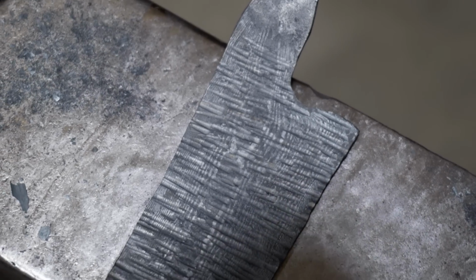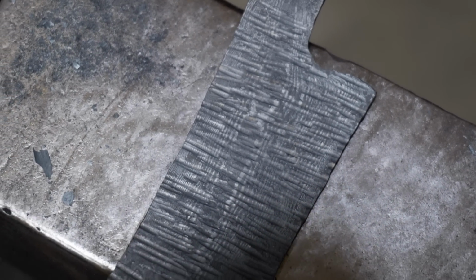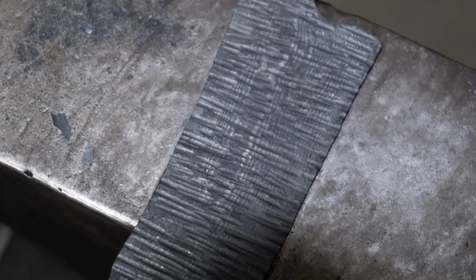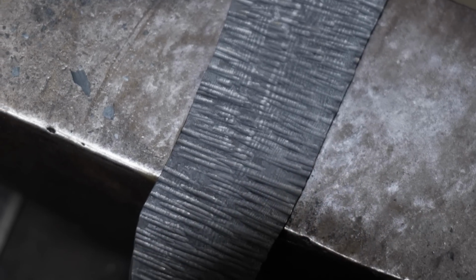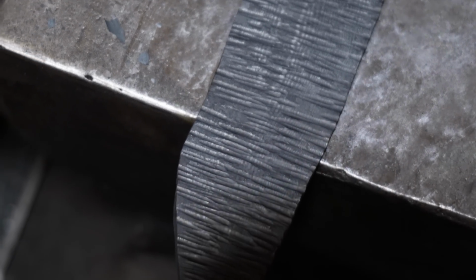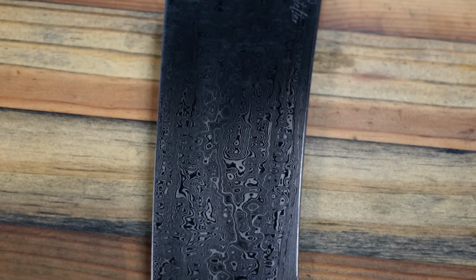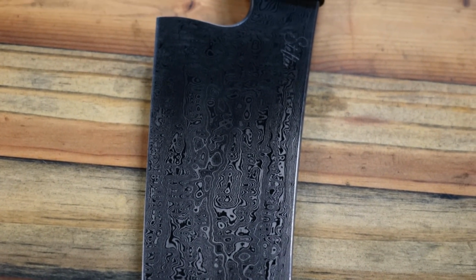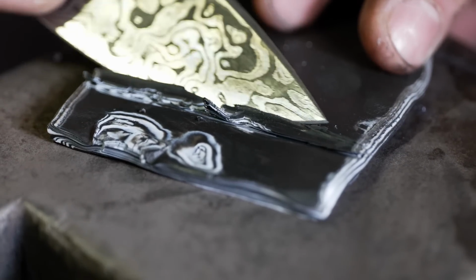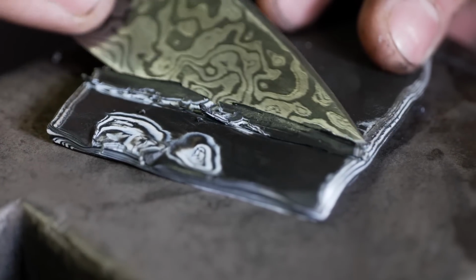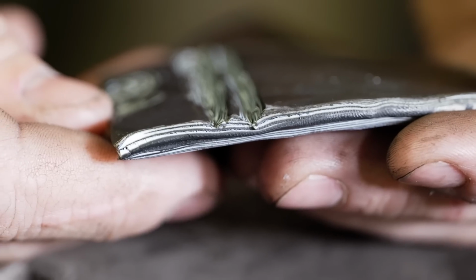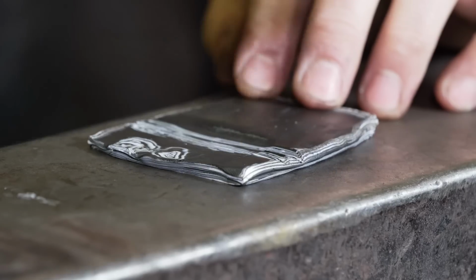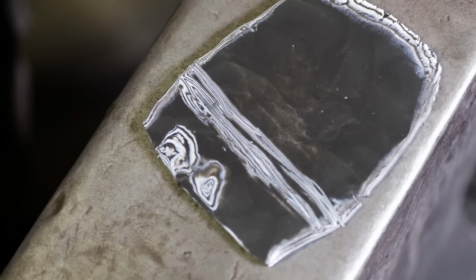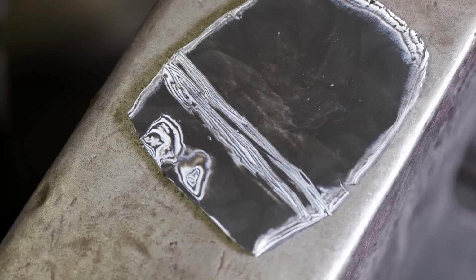You can either forge, press in a pattern to the outside and then grind off the topography, and what happens is you manipulate that straight laminated steel, and then when you grind it down, you show the areas that were ground off. Or you can grind in a pattern. And so if you were to grind in lines and then forge weld it down, you're again going to bring that pattern up to the surface. This is what we call surface manipulation patterns. There's all different kinds of things that you can do with it.